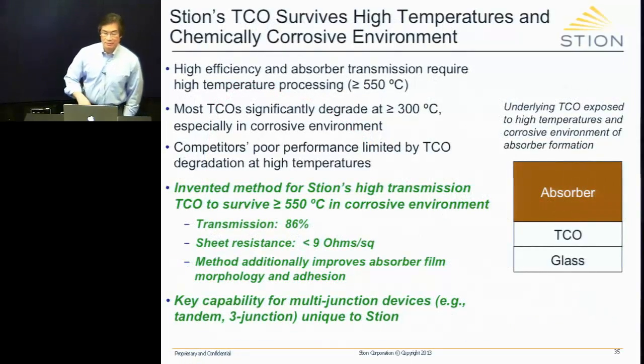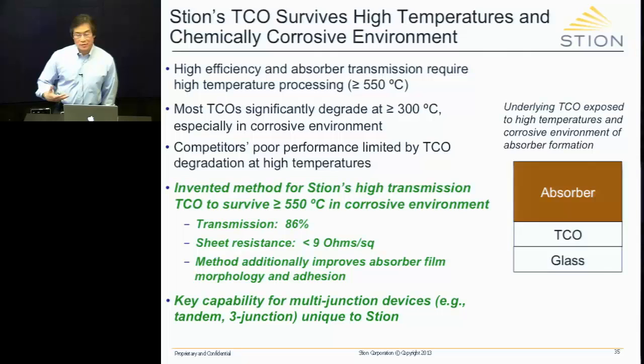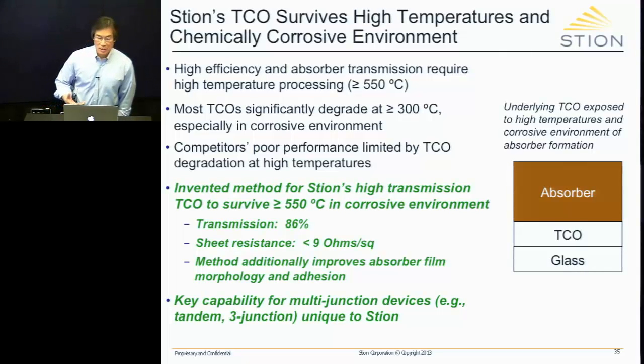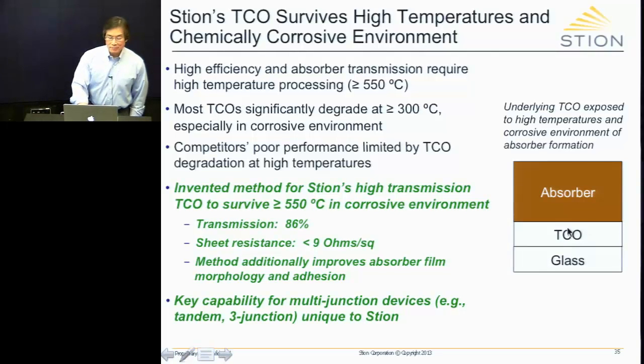Now, another point here is that in chalcopyrites, you have to process the film at very high temperatures and in very corrosive environments. But as you know, all thin films, if you deposit them at very high temperatures, generally tend to do much better because of the effect of the annealing that occurs. Well, unfortunately, the TCO is at the bottom of the absorber, and you have to protect the TCO somehow or prevent it from being degraded. In our case, we process at 550 degrees or higher in a very corrosive environment. Again, I apologize, I can't tell you how we do it, but we were able to solve this problem. It's a very difficult material science problem. It allows us to put the absorber on top of this TCO without degrading the TCO. We can still maintain less than 9 ohms per square with high transmission.